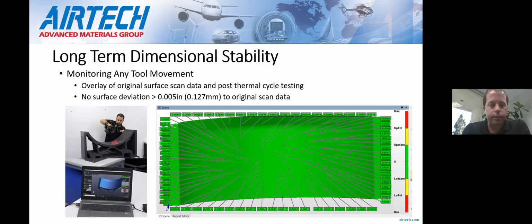Also looking at the dimensional stability. We were laser scanning the tool periodically through the cycle testing. And what you see on the right-hand side is an overlay of the data after thermal cycling compared to the original scan data. So no deviations greater than 0.005 of an inch or 0.127 millimeters to the original scan data. Overall, just great dimensional stability, and really not seeing any failure in that mode either.